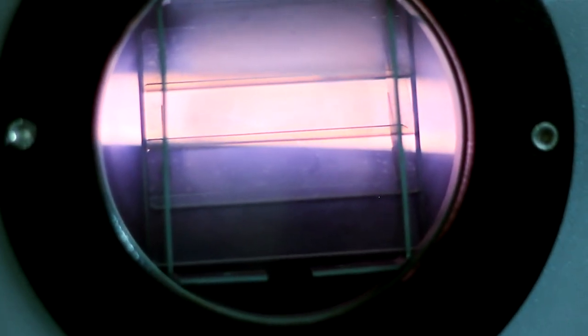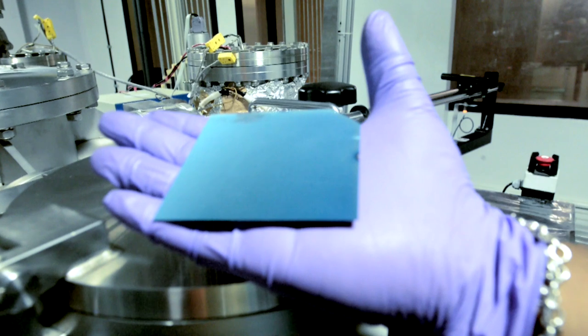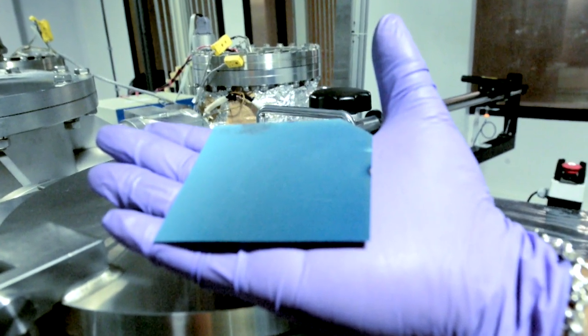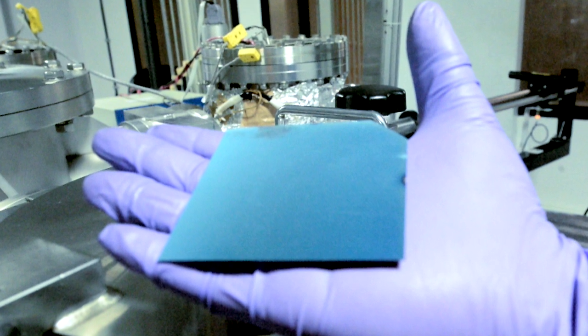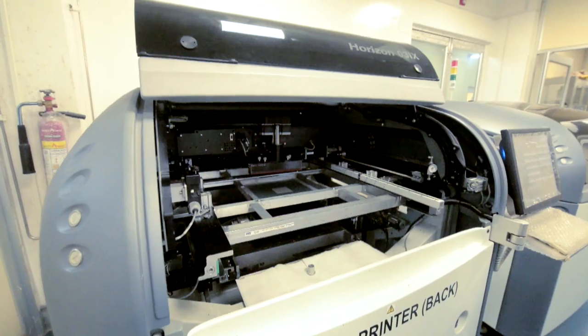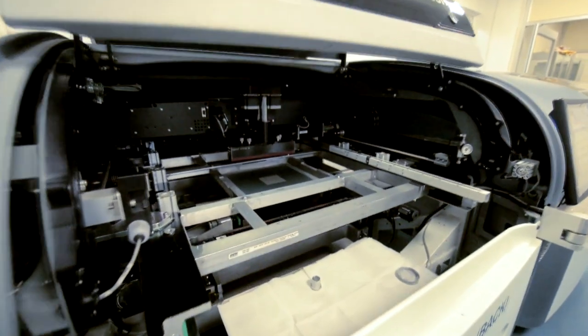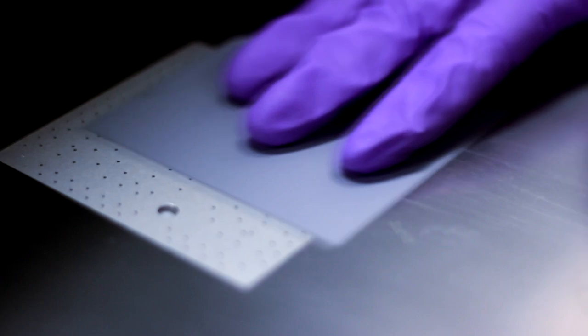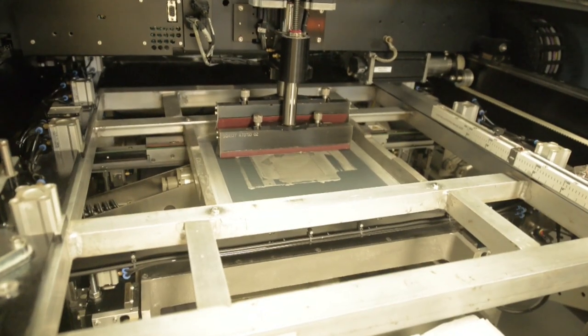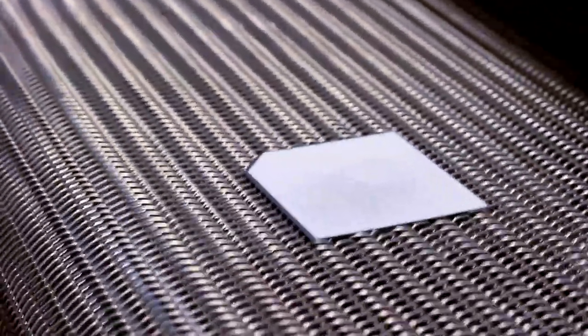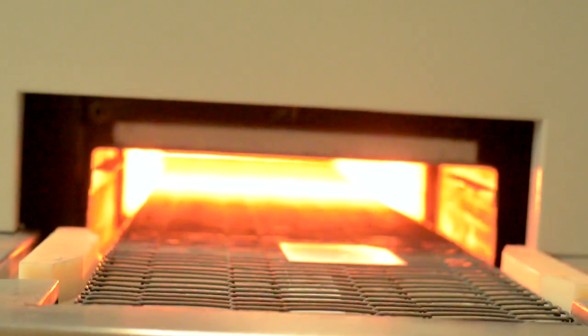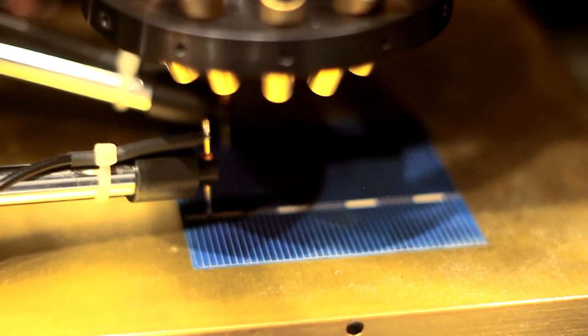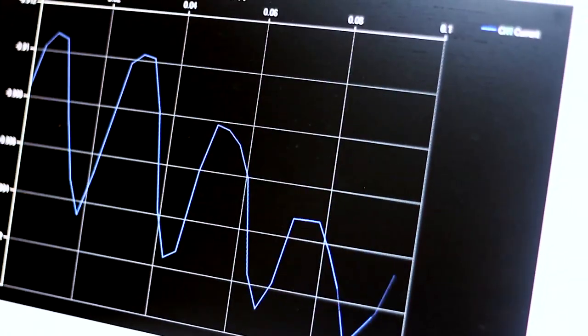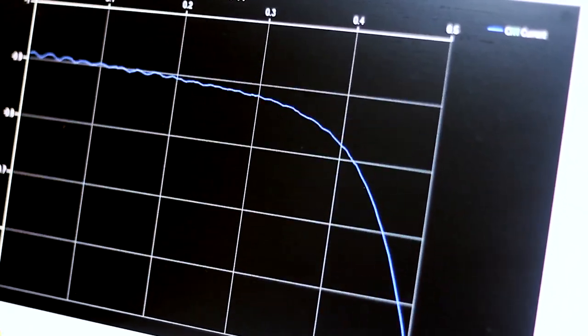Edge isolation of the sliced wafers is then done by plasma etching using fluorine chemistry, and a silicon nitride anti-reflection layer is deposited in a PECVD system involving silane and ammonia gases. Thereafter, screen printing of the conducting pastes is done to realize the back and front contacts in two separate printers, and the pastes are dried in two separate drying belt furnaces to avoid contamination before co-firing in a high temperature belt furnace. The finished solar cell is finally characterized with a sun simulator to obtain the current voltage characteristics.